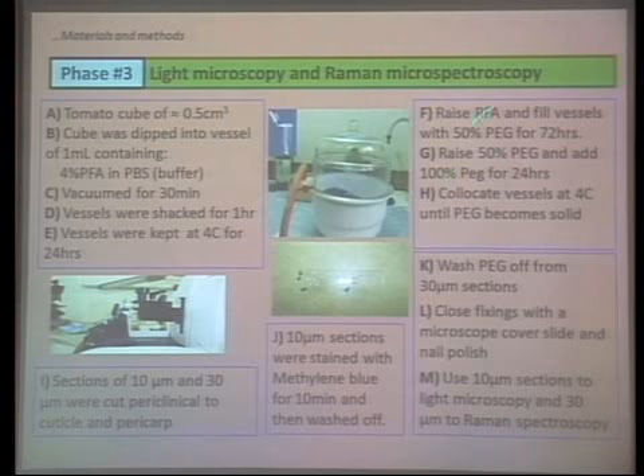We came the day after, we washed off the PFA. We put a solution of 50% PEG for 72 hours. We wash it off. We put a solution of 100% PEG for 24 hours. And then we put it in the fridge so the PEG will become solid. Once the PEG became solid with our tomato cube inside, it becomes something like this when we take it out